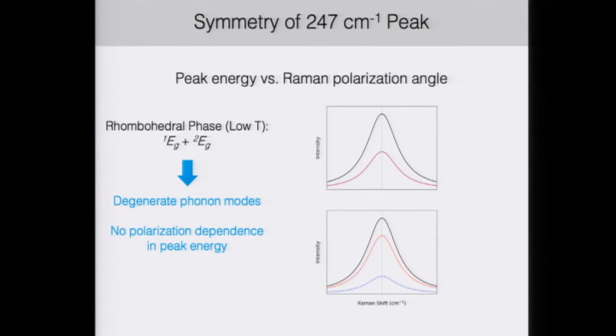So one way to analyze this is to look at the symmetry of this peak that we've been studying. So if you consider the peak energy as a function of Raman polarization angle, in the rhombohedral phase, this peak is actually a set of 2 degenerate phonon modes. So as you change the Raman polarization angle, you'll change the relative intensity between these 2 modes, but since they're degenerate, the overall peak that you actually observe will have no polarization dependence in the energy.